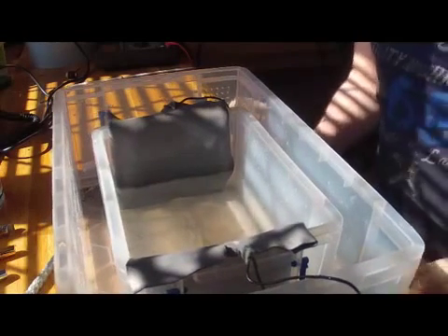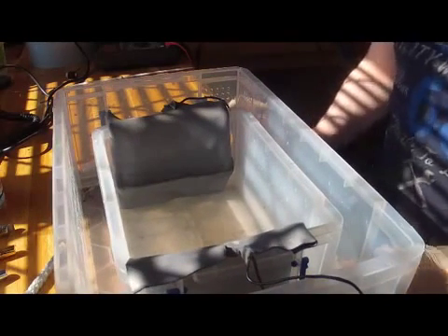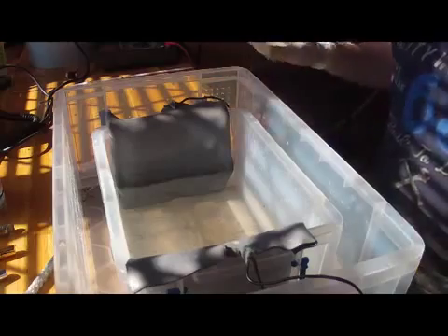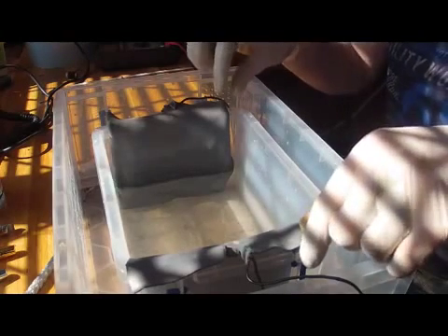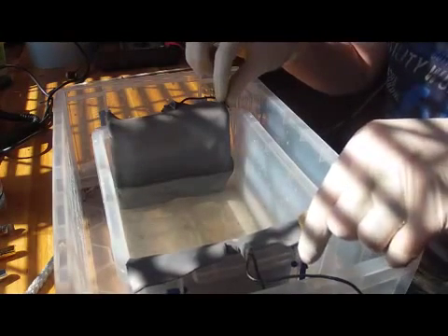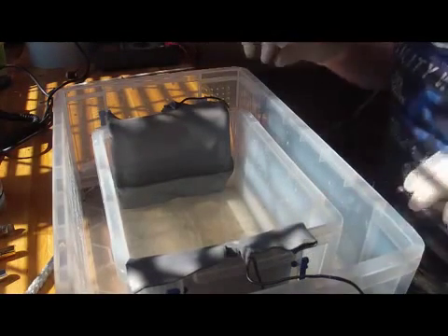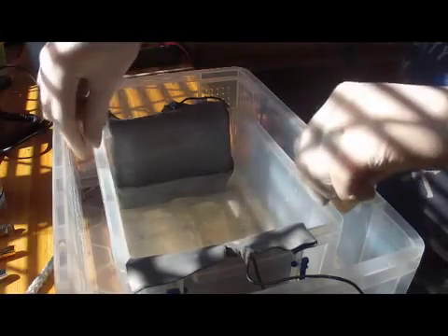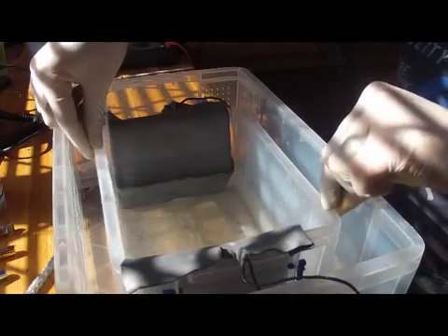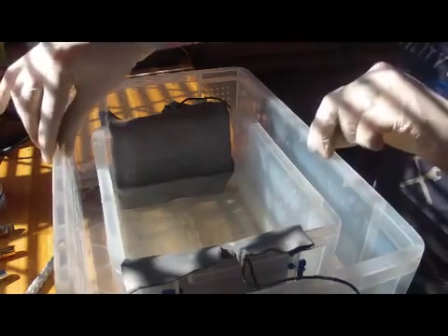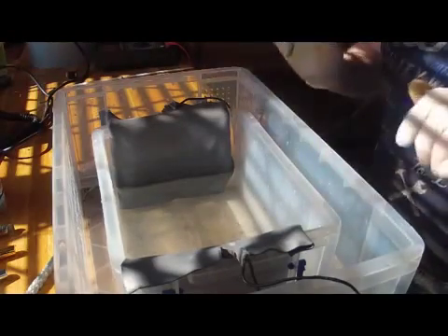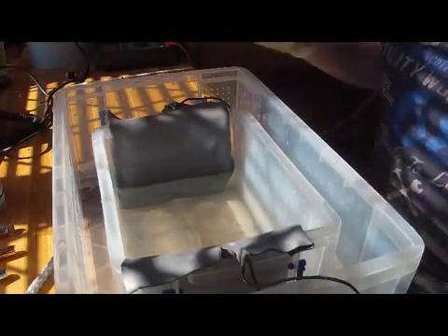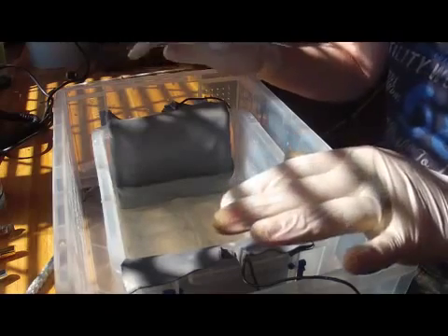And here we have my homebrew anodizing tank. Now, what we have is two lead cathodes, which is just pieces of lead flashing which have torn off and folded over the side of the tank. We have a smaller tank in the middle here and a larger tank on the outside, which is mainly for safety. So if anything was to go wrong with this tank, then the acid would just spill into the outermost tank.